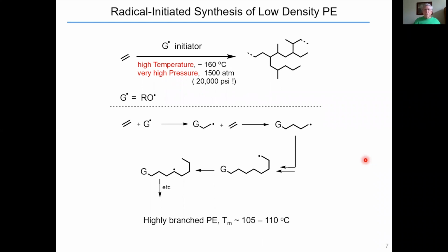Low density polyethylene is often made through a radical process. So we have some initiator here, often an alkoxy radical. These reactions run at extremely high pressure and high temperatures. Ethylene is not very reactive towards radicals. You're generating a primary radical that adds another ethylene, and so on. And that radical can do backbiting. So for example, this radical can abstract a hydrogen atom further down the chain and generate a secondary radical. And this leads to highly branched polyethylene with lower melting points.